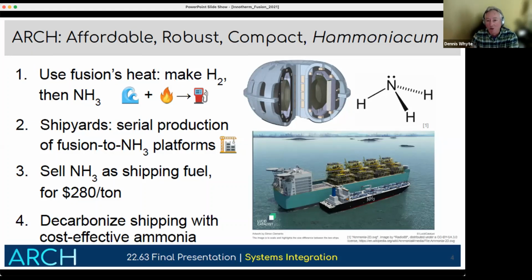So here's the cartoon of it down at the right. Essentially using fusion energy as a fundamental energy source to create a green fuel rather than to make electricity. And what's very exciting, and germane to this, is that the target of this class became not a technical target about some amount of power or power density, but an economic target. We had some external experts tell us that if we could sell this ammonia at about $280 per ton, we would basically decarbonize worldwide maritime shipping. So could we actually get there?